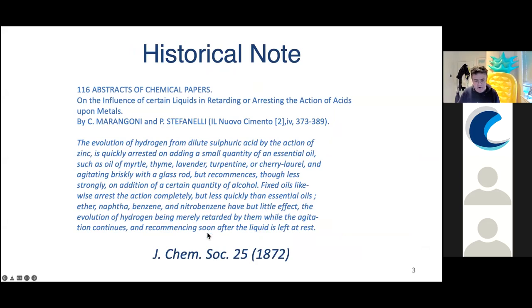So this abstract comes from the Journal of the Chemical Society all the way back in 1872. And they're reporting work, and forgive me for pronouncing it wrong, in a publication called Il Nuovo Cimento. And these two characters here, Marangoni and Stefanelli, did some work where they were looking at hydrogen evolution, so corrosion, in sulfuric acid on zinc. And they were adding various oils, such as myrtle and thyme, and they were reducing the corrosion rate. They don't mention the word corrosion inhibition here, but that's probably what is going on, that something's forming on the surface, inhibiting these processes. So it's been around for a long time and very widely applied.